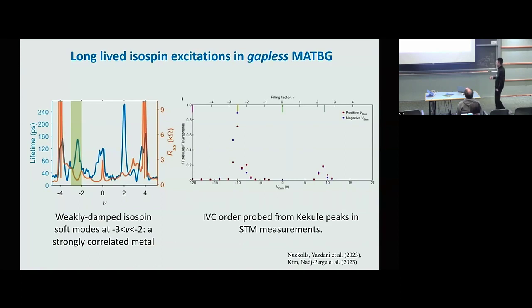And this can be identified from the Kekule peaks in STM, the Fourier transform of STM. And we can see that on the hole side, there's a strong IVC order between -2 and -3. And on the electron side, there also seems to be some IVC order near +2. So that's kind of interesting. They seem to match pretty well.